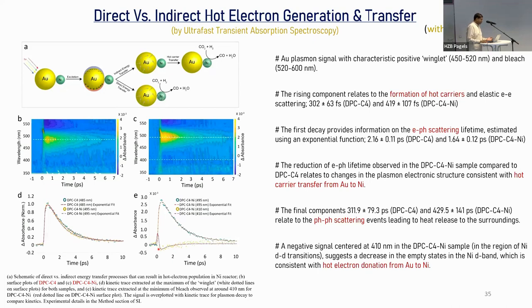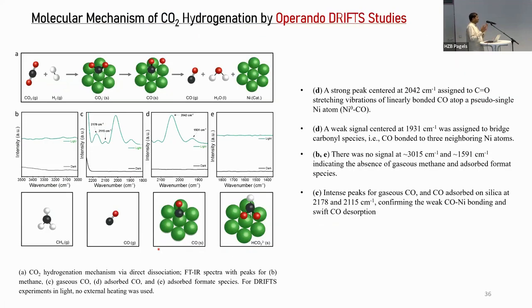So now, in addition to understanding whether it's an electron-mediated or thermal-mediated reaction, we also tried to understand the molecular picture. How does the CO2 adsorb onto the nickel, how does it convert into a product? And what we observe, using in situ DRIFTS studies, is that CO2 adsorbs onto the nickel and directly dissociates into CO and oxygen. See, there is no hydrogen required if you really want to see this particular shape. CO2 can directly convert into CO and oxygen. And CO then desorbs, and the electric field plays a role in the CO desorbing. But your nickel becomes nickel oxide, no more active.